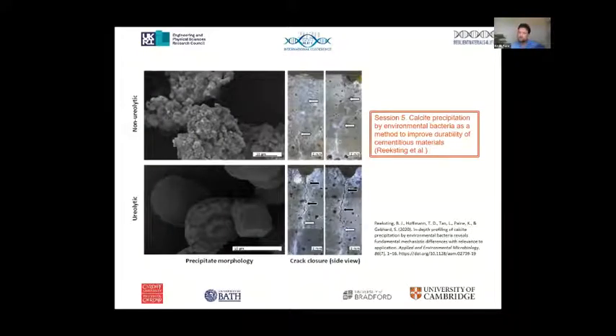And we found that in terms of self-healing of concrete, both the ureolytic and non-ureolytic bacteria that we used were capable of closing cracks. But interestingly, we found that the non-ureolytic bacteria, at least in the conditions that we tested them, worked slightly better. So we got slightly greater healing here than we did with the ureolytic ones. This was to some extent a surprise, but it meant that this was the pathway that we were then able to largely proceed.